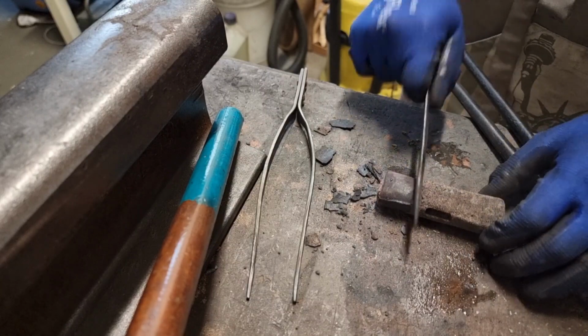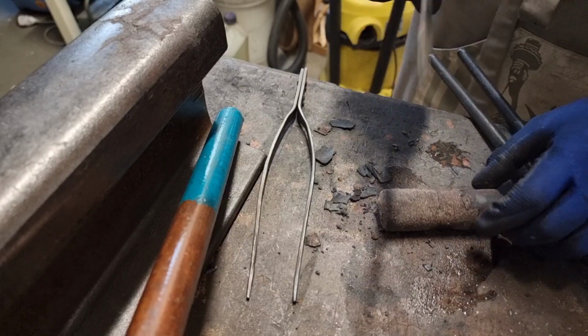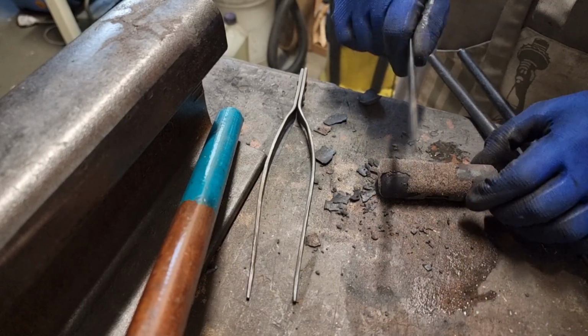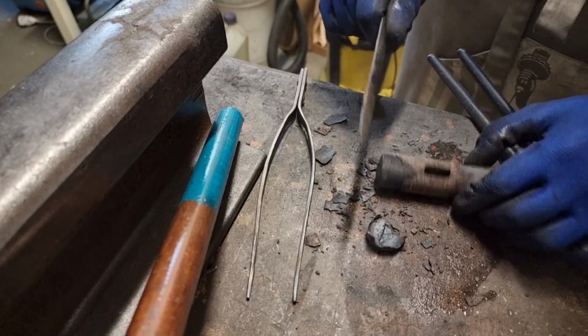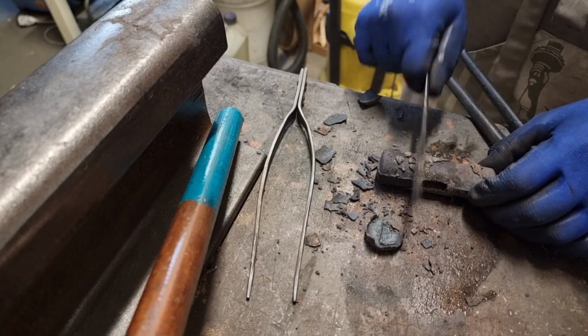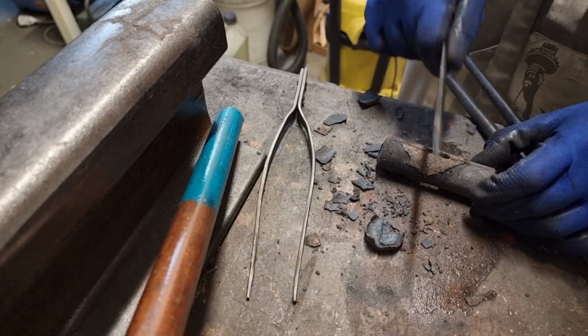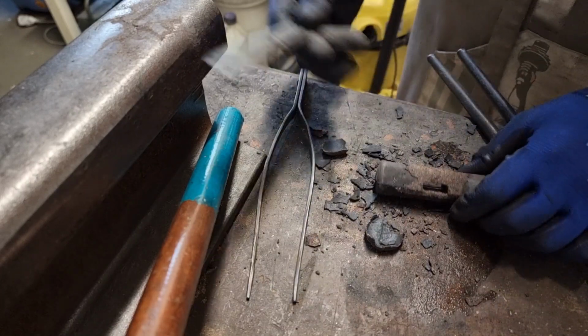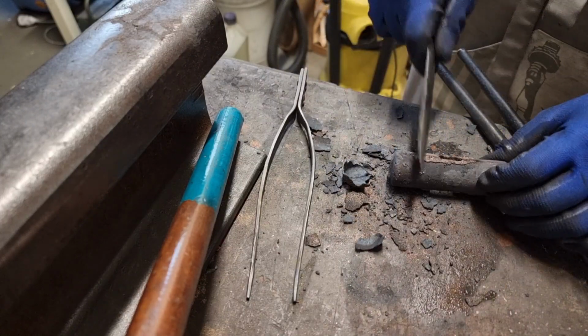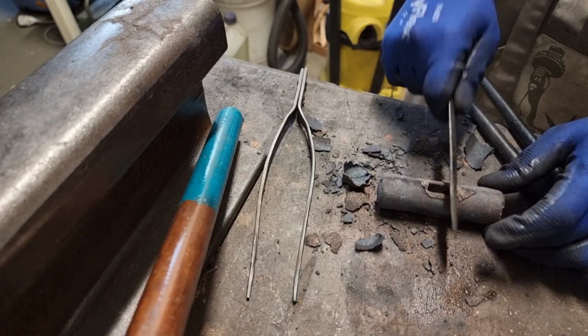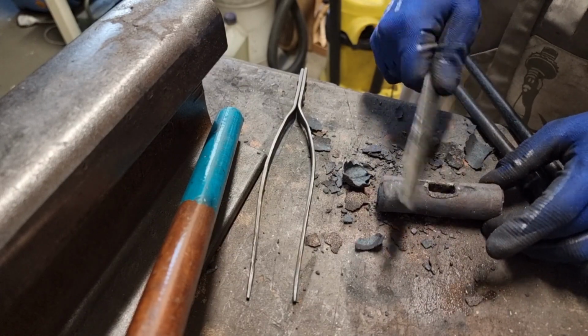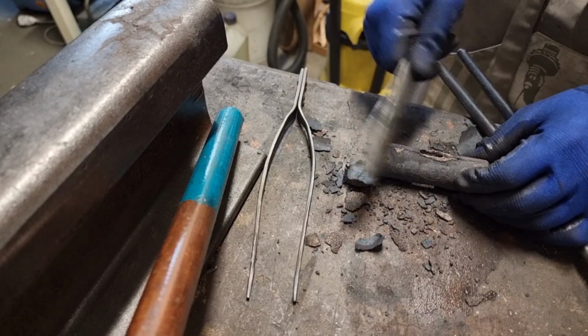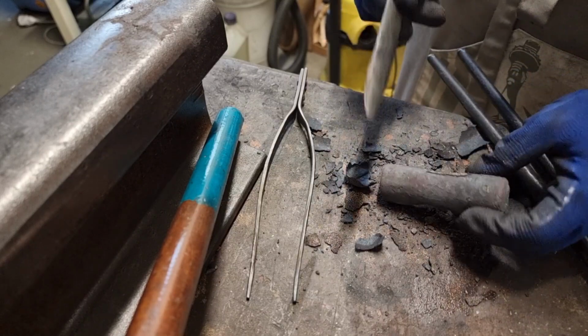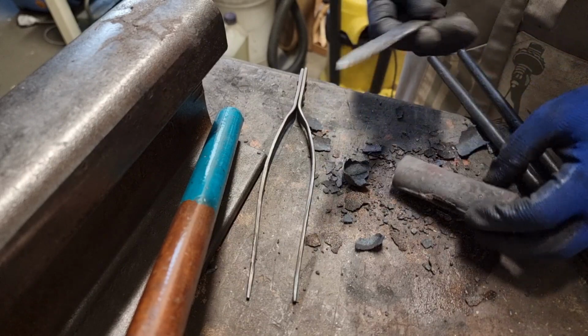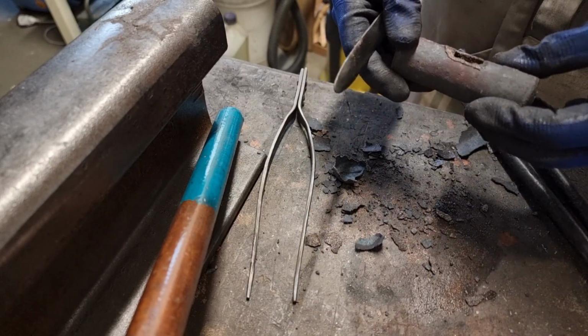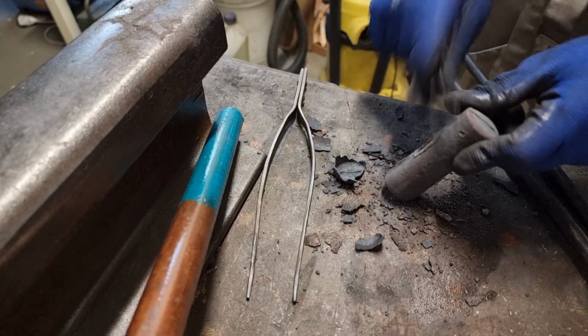If you leave the iron too long in the sand, and if you go too excessive with the temperature, then you get this really thick layer of oxidation on your iron. So this is something you don't really want to get. So I recommend staying below that 900, or in the range of the 900 centigrades region. Anything above that is really eating on the iron excessively. And also make sure that you keep your iron in a good layer of sand, packed in a good layer of sand, that also prevents excessive oxidation.